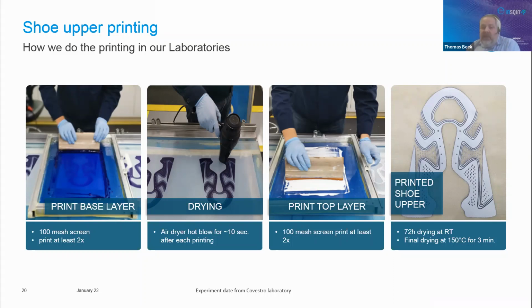After we have mixed the printing paste and adjusted the rheology, we do the base layer, printing at least 2 times. We then dry briefly with a hair dryer, 10 seconds after each printing. Then we can directly apply the top layer, again pre-drying with the hair dryer between each printing. Then we let the system dry for 72 hours at room temperature before we do the final drying at 150 degrees for 3 minutes.